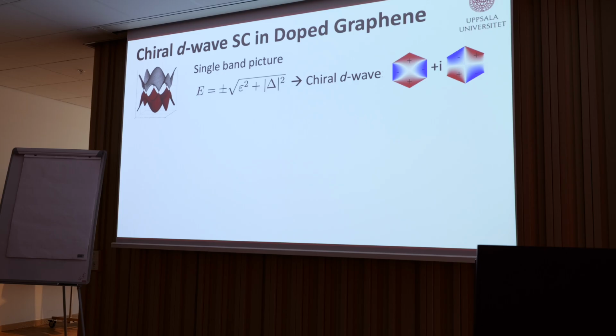Because if you take doped graphene, you have this band structure, graphene with a Dirac point here, and it's doped just here, say, up in the gray region. It's a single band picture. I can think of my quasi-particle energies just following this form here. So this is just the kinetic energy and the order parameter. If I sit on a Fermi surface, this is 0. And then if I want to gap out all my states, I want to have an order parameter that doesn't have any nodes.